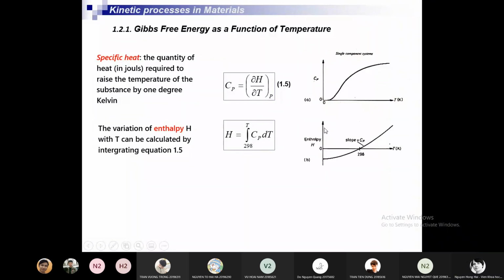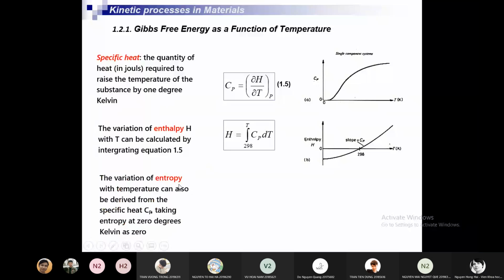Okay, so this is the graphic: the enthalpy curve versus the temperature. The slope of this curve is the specific heat. And at this temperature, 298 degrees Kelvin, the enthalpy is zero. So we have the enthalpy. And then the variation of the entropy with temperature can also be derived from the specific heat, taking the entropy at 0 degrees Kelvin as 0. So the entropy of any system at 0 degrees Kelvin is equal to 0.